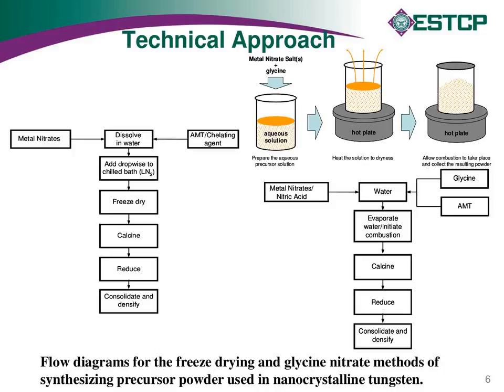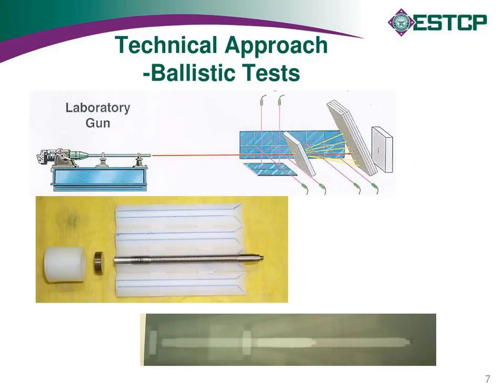Slide number 7, just a couple of quick things, more details on the technical approach, this ballistic test, just a schematic showing how we do those kinds of tests here at the lab. We do ballistic comparisons against actual RHA, rolled homogeneous armor plate. You see in the yellow box there the example of a laboratory sabot, so we can put the material in a launch package. It's pushed out of our lab gun through our experimental setup, which has X-ray equipment to measure velocity, to measure the pitch and yaw, because that can really push your numbers around. So you've got to verify you have good pitch and yaw at impact, and then look at the residual velocity out the back, or how much penetration into steel that you actually have.